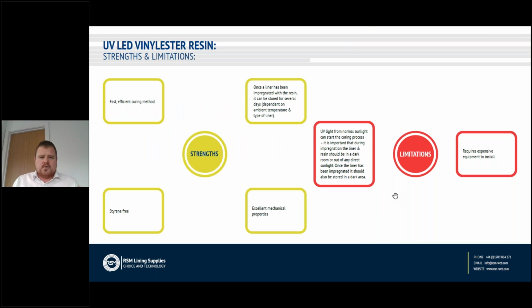In terms of the pros, we've got a really fast, efficient curing method with a full background of data so that we can see exactly how the liner was cured, the temperatures achieved, the speed of cure. We have complete traceability of the curing process. Once the liner has been impregnated, it can be stored for several days depending on the ambient temperature, ensuring that we keep it out of direct sunlight.